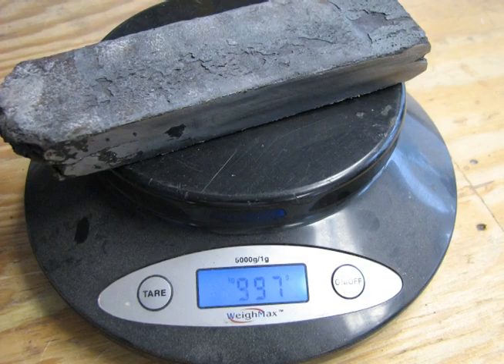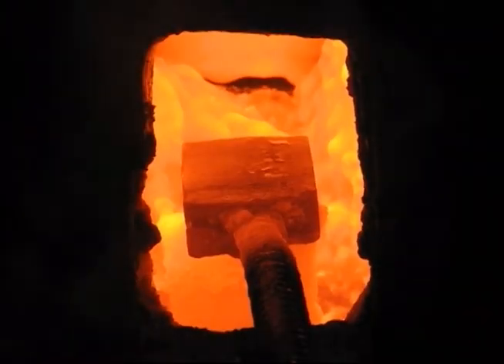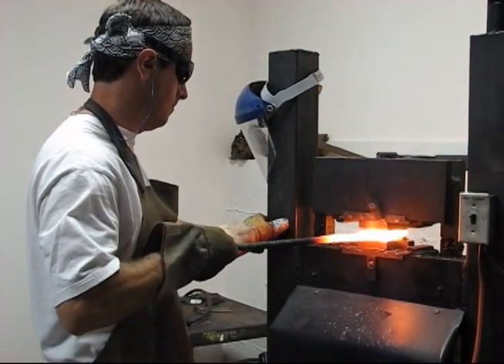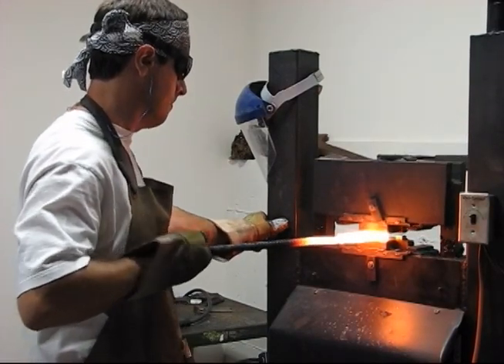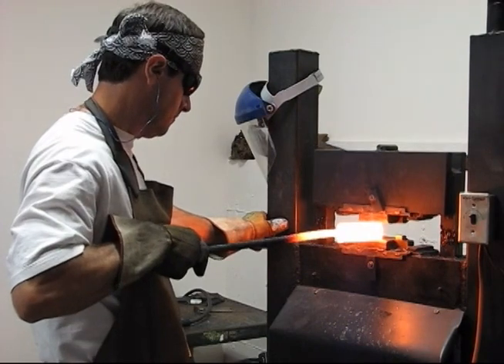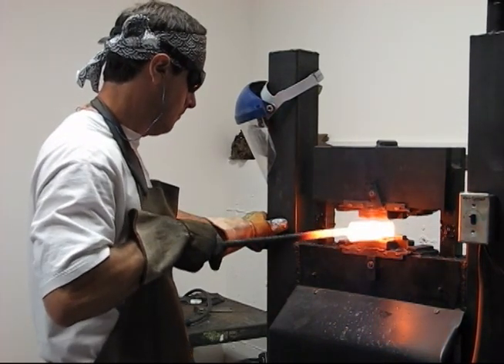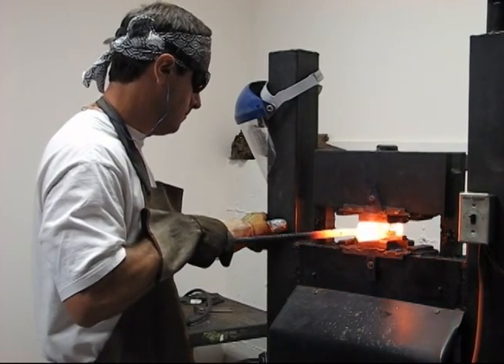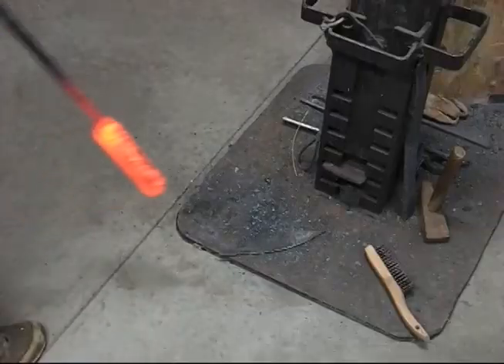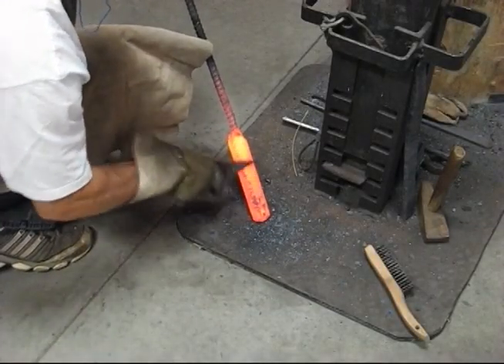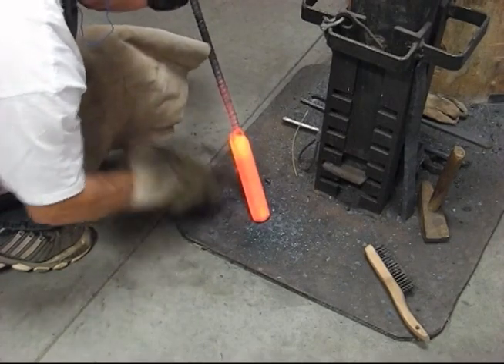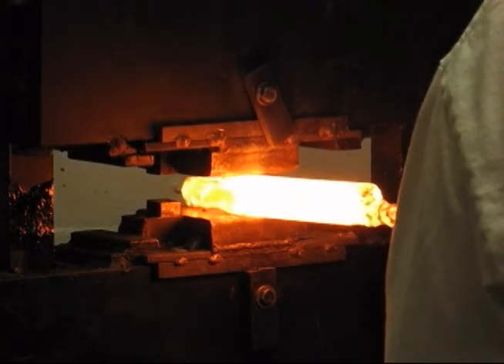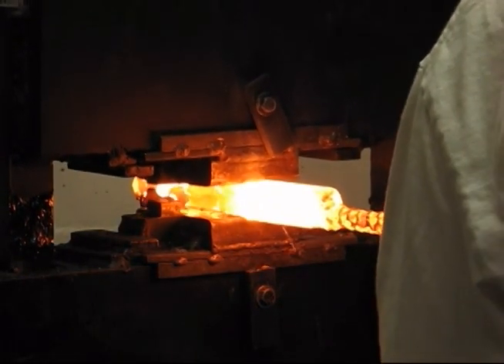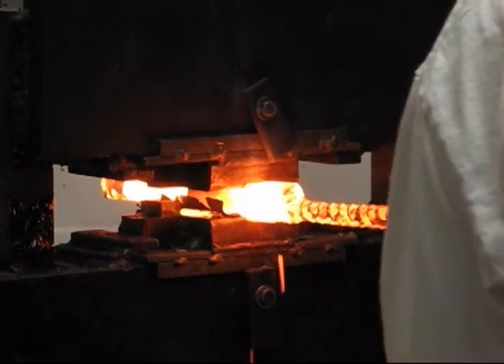A little bit of ferric chloride helps visualize the pattern. This bar weighs about 1 kilogram. Jesus will start by drawing it out using the press, making sure to keep the bar as clean as possible by scraping the scale off. Fortunately, this bar is also behaving quite nicely under the press, allowing for heavy reductions in thickness without delaminating.